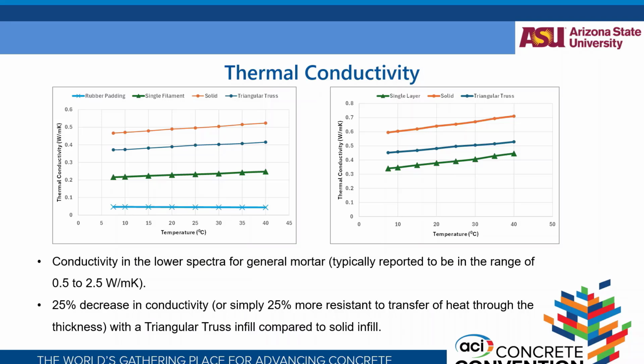Again, the conductivity will vary based on the different average temperature of the section, so you can see the trend that it goes. But typical values for the conductivity are in the lowest spectrum of the ones reported in literature, which are generally within the range of 0.5 to 2.5 watts per meter Kelvin. We are around 0.65 average for the solid infill, while for the other infills, we are in the range of 0.4 to 0.5.